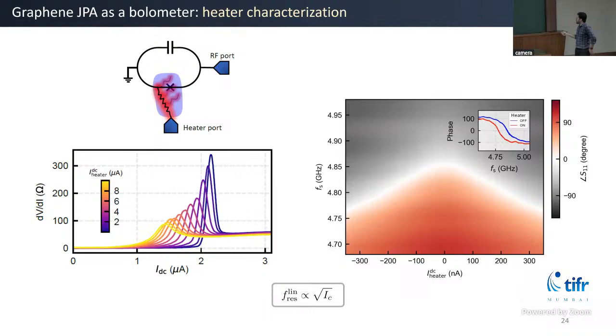So once we are done with the DC experiments, we move to microwave experiments. There we are probing the reflection coefficient S11, the phase of that, as a function of heating and the signal frequency. And now we see that when you increase the heater current, the resonance frequency goes down because it heats the Josephson junction.